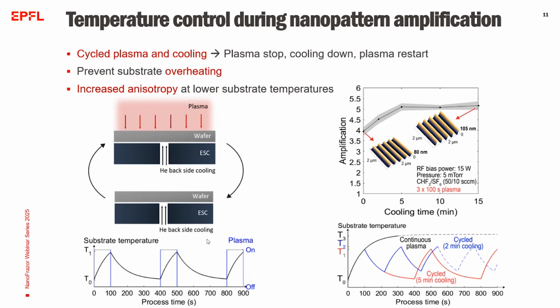And by benefiting that, we found that incorporating 5 minutes of cooling cycles between 100 seconds of plasma etching cycle effectively mitigates the overheating issues and improves the amplification of the pattern transfer, and it makes the process much more repeatable. So independent of how much time you put in the plasma etching, if you divide 200 seconds of plasma into cycles and prevent the substrate from overheating, you can get more repeatable amplifications.